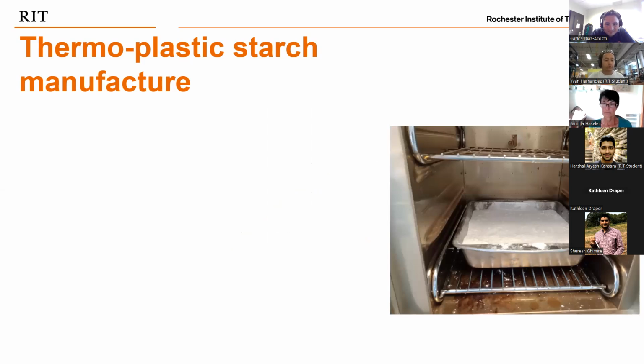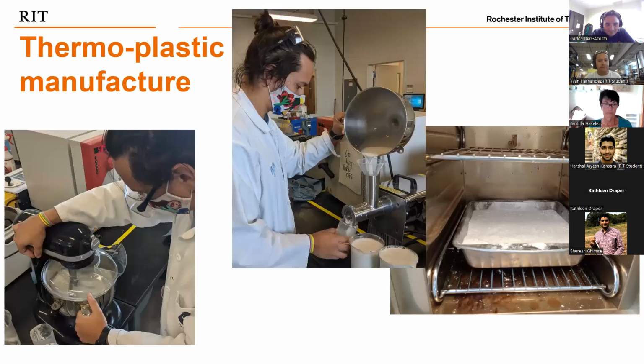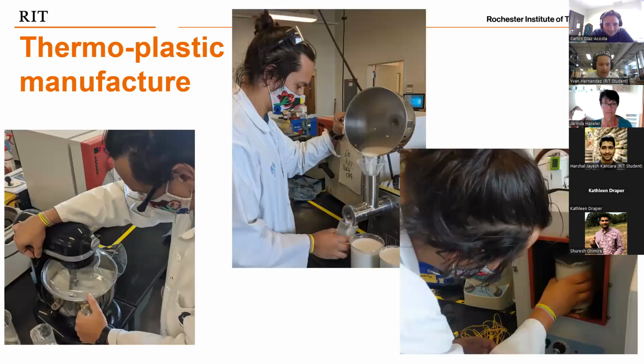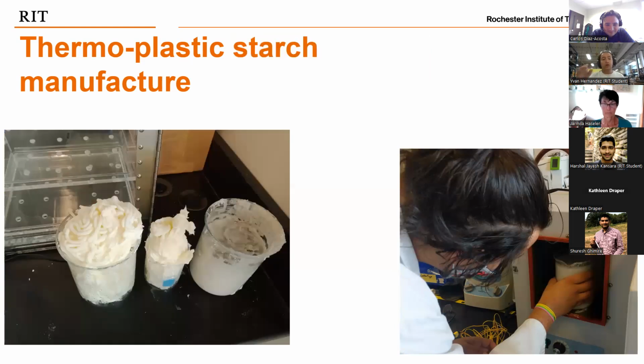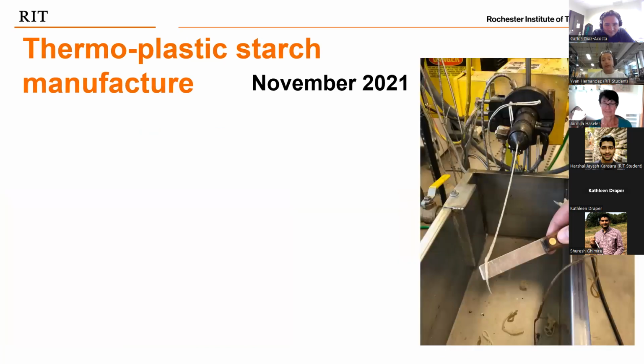You have to dry it, then you mix it, then you grind it, then you heat it again, then you repeat that process 3 times to get that powder that you have in your kitchen all the way to a paste that you can actually extrude. Oh, sorry, I'm in the lab, so there's some noise. And so that paste we were able to extrude from a single screw extruder, sorry.